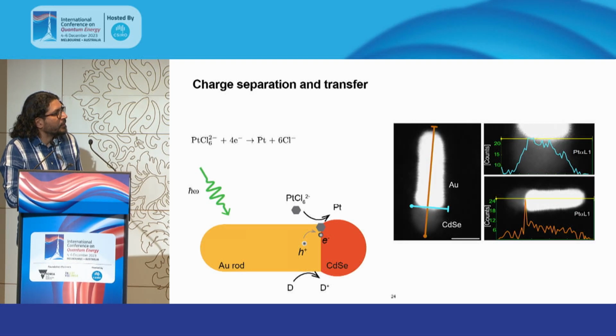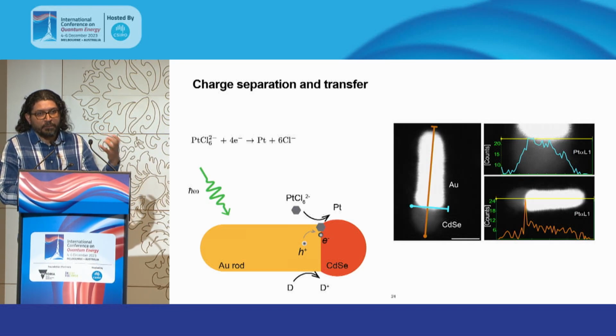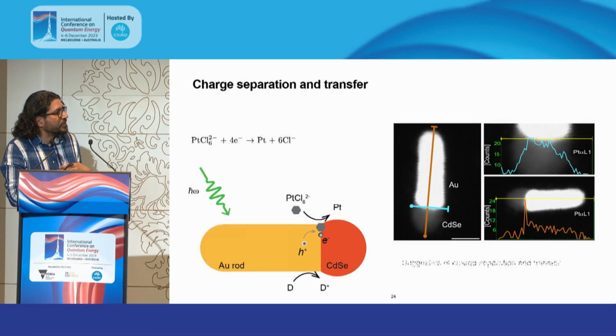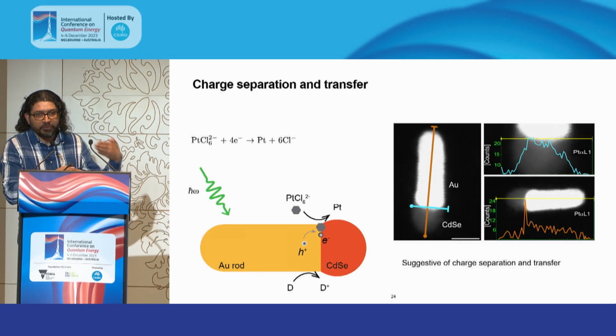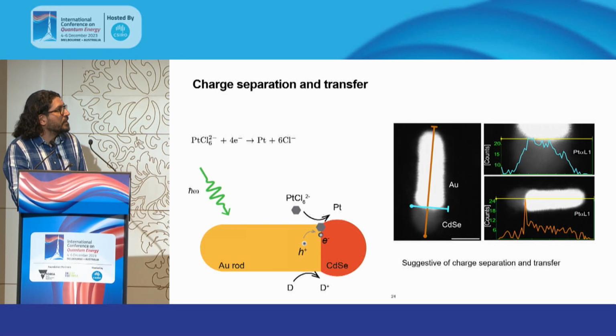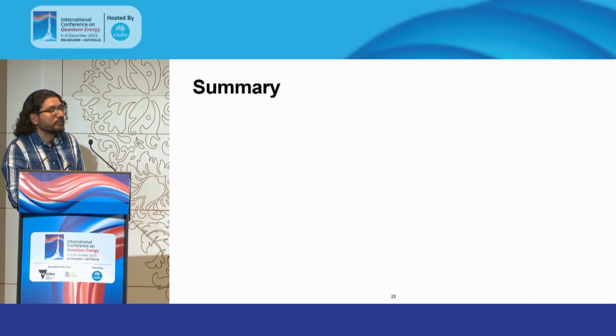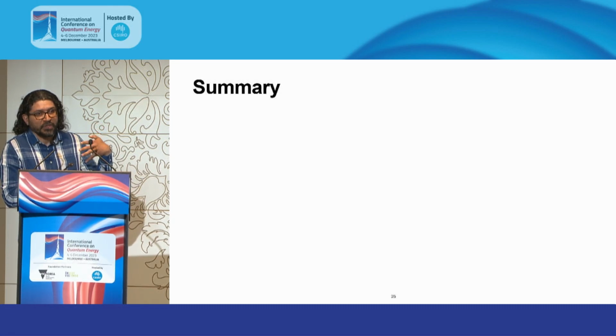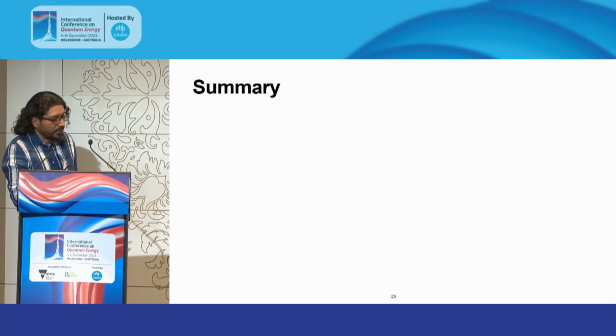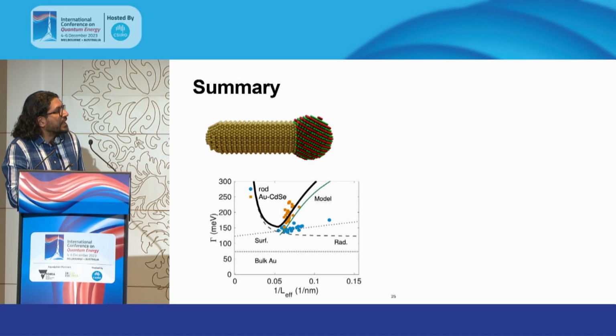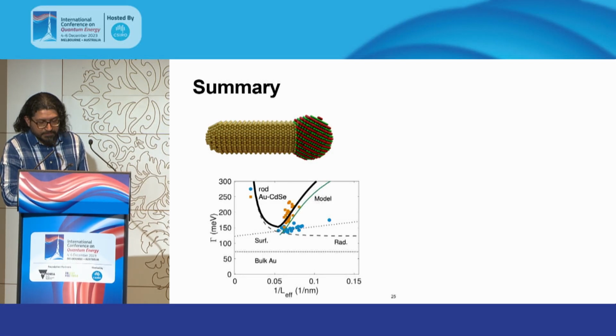So we did the experiment. Then we brought the sample back into the electron microscope and did single particle imaging, but this time we were mapping for the presence of platinum. As you can see here, platinum tends to accumulate first at the interface, giving us confidence that we are measuring electron transfer from the gold rod into the semiconductor tip. And we do that with over 40% quantum yield. So we are leading the field in converting incident photons into electrochemical potential using metal semiconductor nanostructures. And that brings me to the end of the talk. Thank you so much for listening.